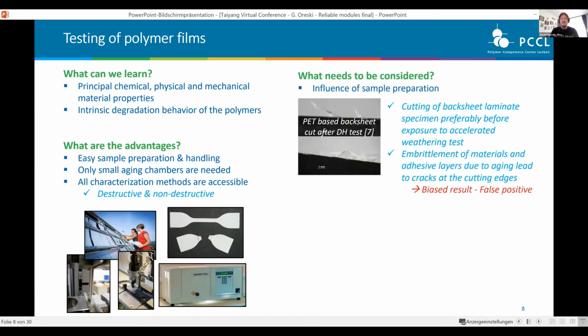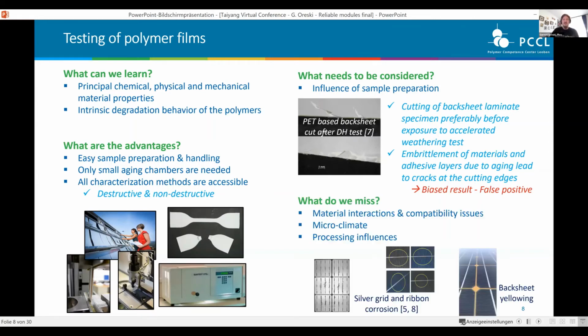What needs to be considered? Influence of sample preparation, for example. When you do some aging studies of your backsheet, please cut your specimen before you put it into a climate or a UV chamber. Because if you just expose a film and then cut it afterwards, the material has already embrittled, and you see these nice cracks forming. What you get is a biased result, a false positive degradation behavior. That means degradation starts earlier just because of these cracks, which have a notch effect and, for example, lead to further backsheet cracking in the end.